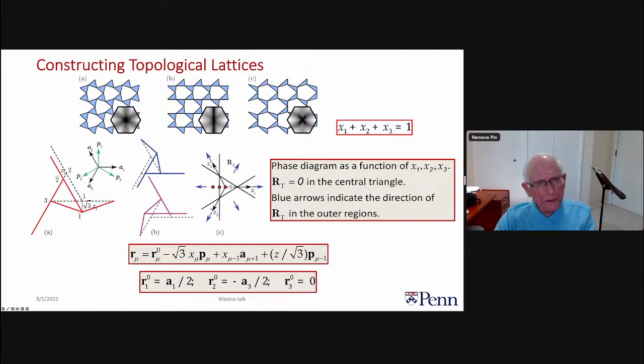There are complicated formulae that tell you how you twist these things so that you preserve straight lines and so forth. Basically, you distort the lattice along directions P and A. A is the direction of the unit cell directions, and P basically are the directions of the conjugate reciprocal lattice vectors. And so you have this formula. When you apply it, we go from here to here, and we keep the sum x1 plus x2 plus x3 equals 1, and you get a phase diagram expressed in the x1, x2, x3 plane, where the center is what we call the twisted Kagome lattice. It has no polarization.